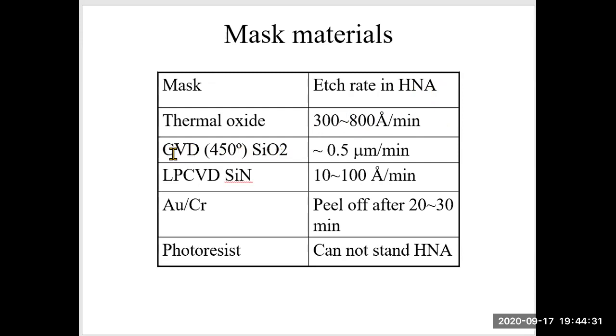CVD silicon dioxide, chemical vapor deposited silicon dioxide. Its etch rate in HNA is very high, 0.5 micron per minute. So typically we do not use CVD silicon dioxide as a masking layer for HNA. Its etch rate is too large. LPCVD silicon nitride, low pressure chemical vapor deposition. Later we will discuss this technology. LPCVD silicon nitride has actually a very small etch rate in HNA, 10 to 100 angstrom per minute. So this is actually an excellent masking layer.